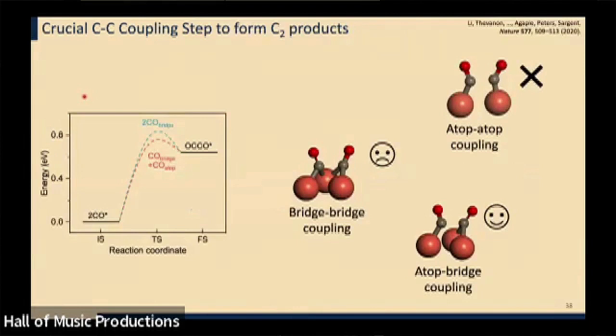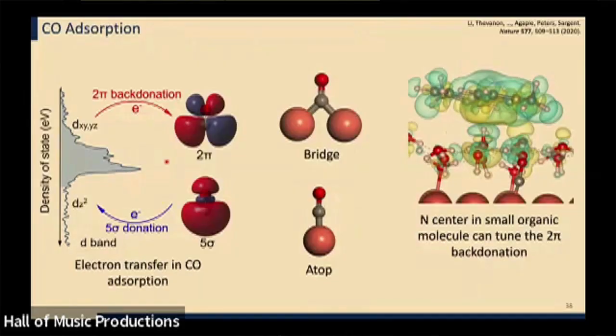And in early computational studies together, we predicted that the way in which the carbon monoxide intermediate, the CO star intermediate, on one of these catalysts was bound, in one of these two possible configurations, the atop or the bridge, it looked like this could really influence the carbon-carbon coupling step. So this key step along the way to the formation of a multi-carbon, a C2 intermediate that's along the path to ethylene. And then we asked, how could we influence that? How could we influence that physical chemistry? And with our colleagues, realized that if we could put a layer of organics, of molecules, right near the surface of the catalyst, near where the CO was bound, we could potentially tune the energetics. So we could really tune the environment or the interaction between the CO adsorbate and the catalyst from above.